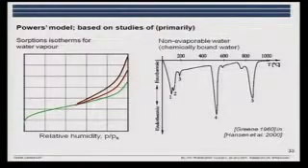Sorption isotherms for water vapor, determination of the amount of non-evaporable water. Here it's shown as a thermogravimetric analysis, but you could also do it by just heating your sample up from 105 to 1000 degrees Celsius.